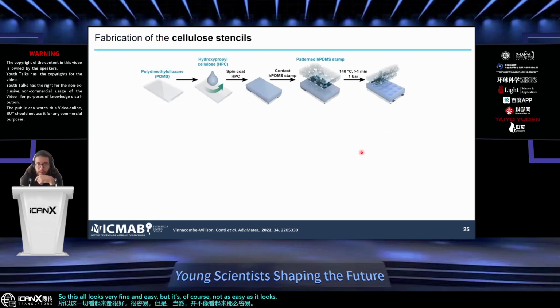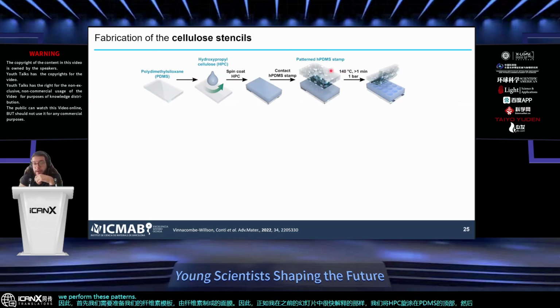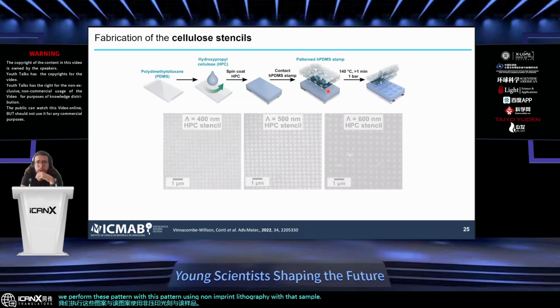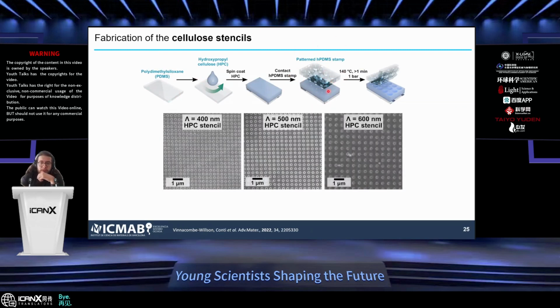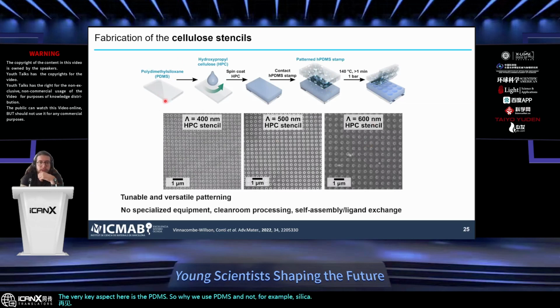So first of all, we need to prepare our cellulose stencil, the mask made by cellulose. As I explained very quickly in the previous slides, we spin coat our HPC on top of the PDMS, and then we perform this pattern using nanoimprint lithography with that hard PDMS stamp. The very key aspect here is the PDMS. So why do we use PDMS and not, for example, silica? And the reason is that